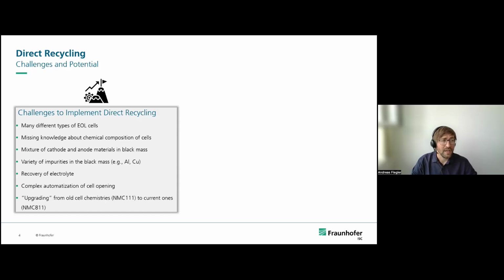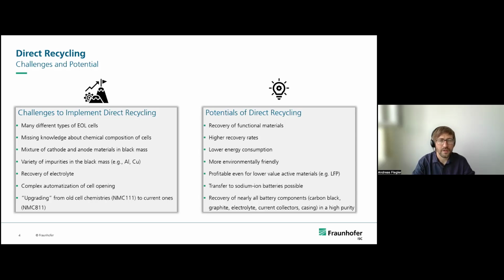And also a topic is how we can upgrade older cell chemistries like the NMC 111 to newer ones like the NMC 811. But the potential of the direct recycling approach is very high, so we can get the active materials with their structure back. So we have the NMC or the LFP in this structure. We have very high recovery rates and green processes. So here we can use water-based processes, which we heard about in Emma's talk. And it's also profitable for the low-value active materials like LFP and sodium ion, which are coming to the market in increasing numbers. And also we can recover the other battery components, so also the carbon blacks, the graphite, the electrolyte, the current collectors, and the casing in high purity.